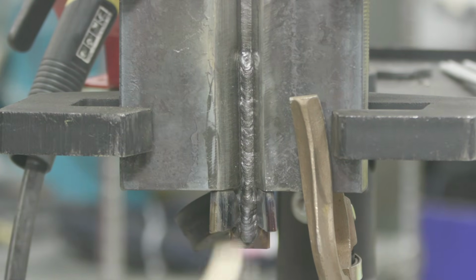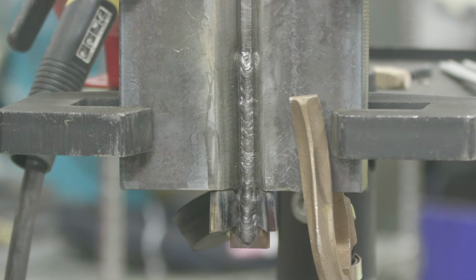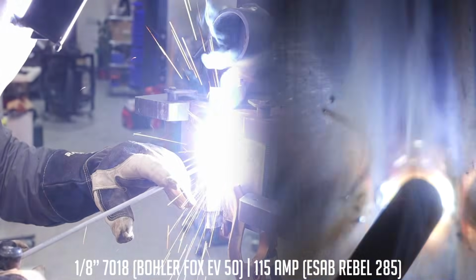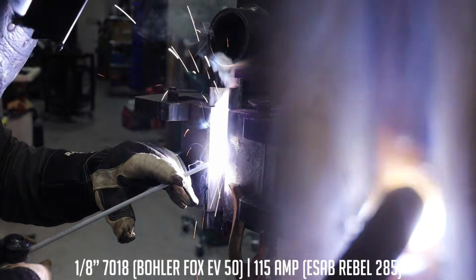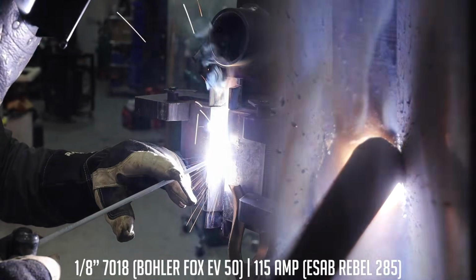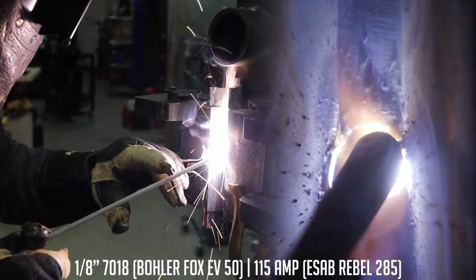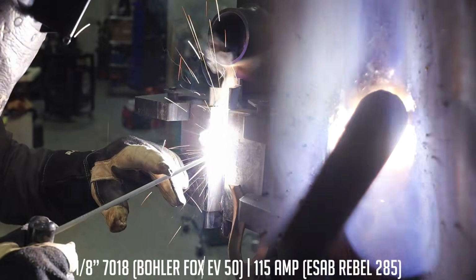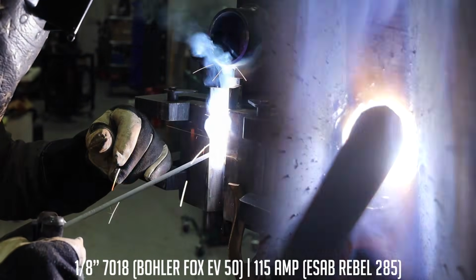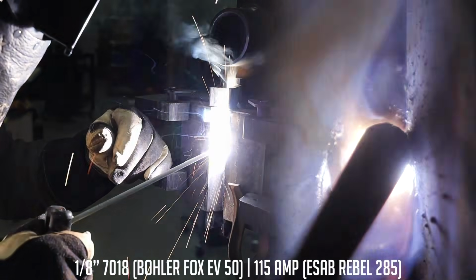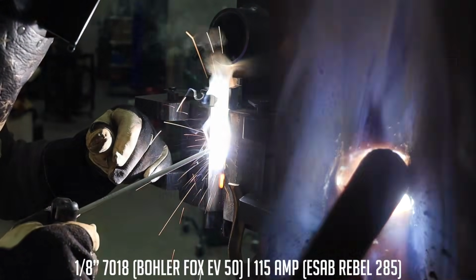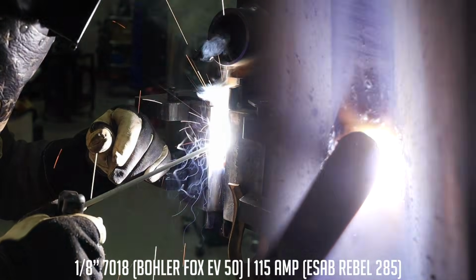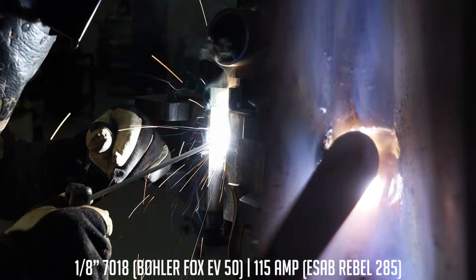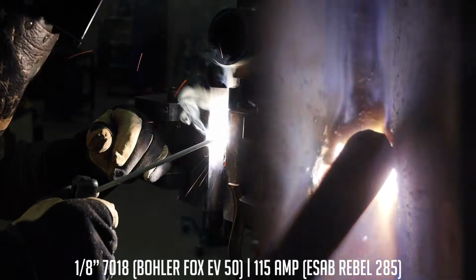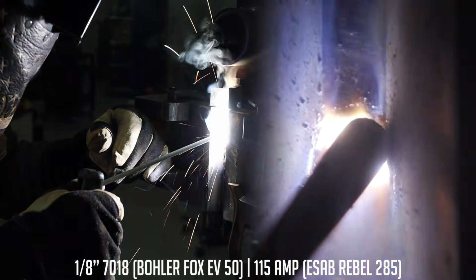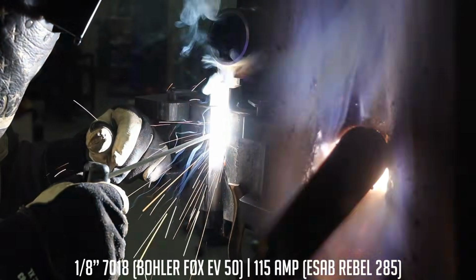So we'll go ahead and perform the tie-in. What I typically like to do is use 2 hands, wrap that up just like that, scratch about 3/8 above that crater, drop back into it, and then slowly start moving my left hand out of the way and pick up like I never stopped with the rod. Try to maintain that nice uniform bead profile and not get any cold lap on that tie-in. With this, I'm really focusing on the side of those bevels. I want to break that down, make sure all this gets tied in and becomes solid weld metal.